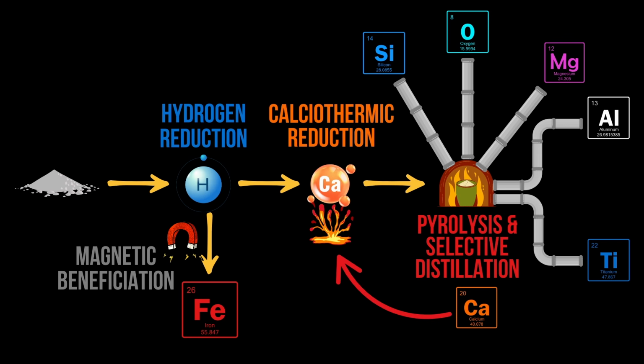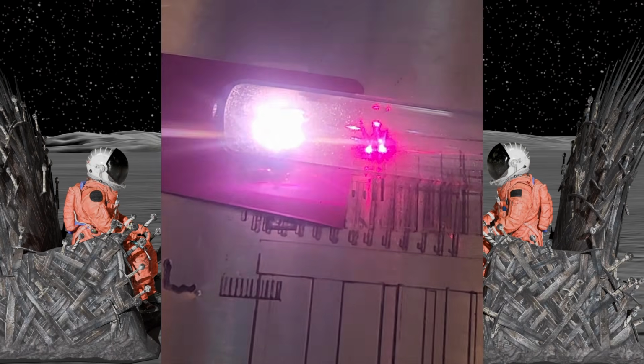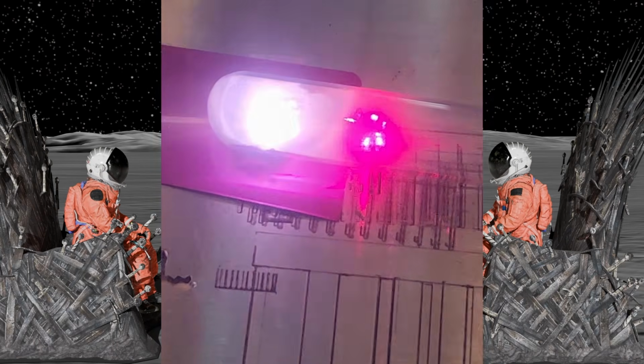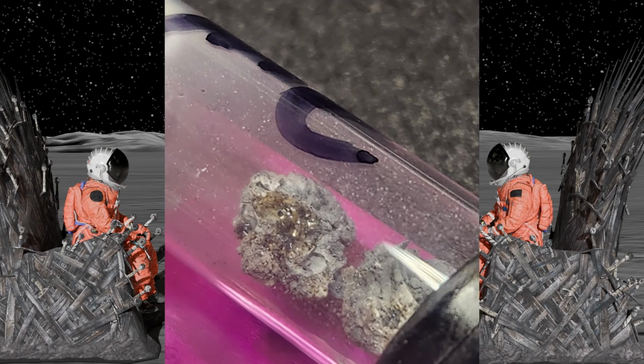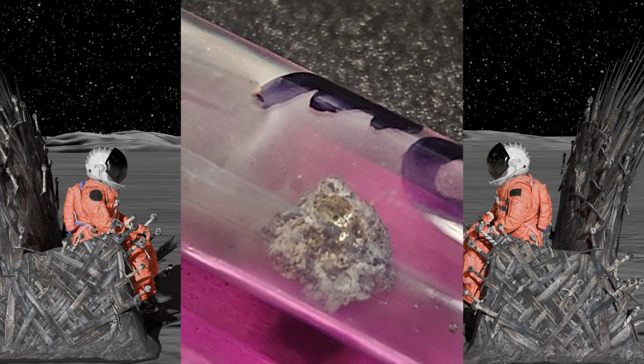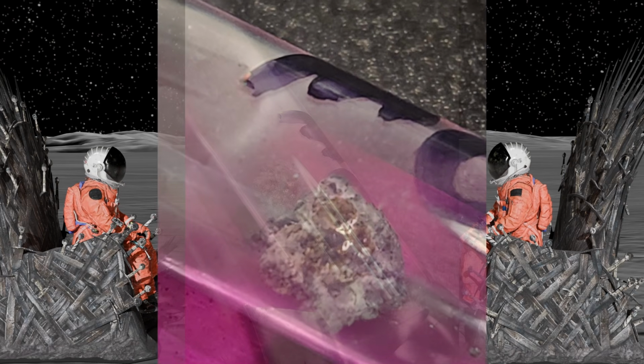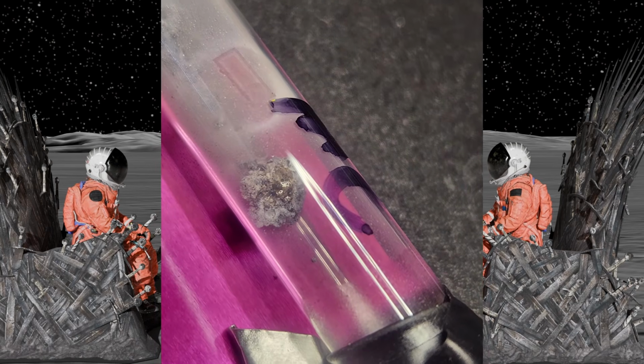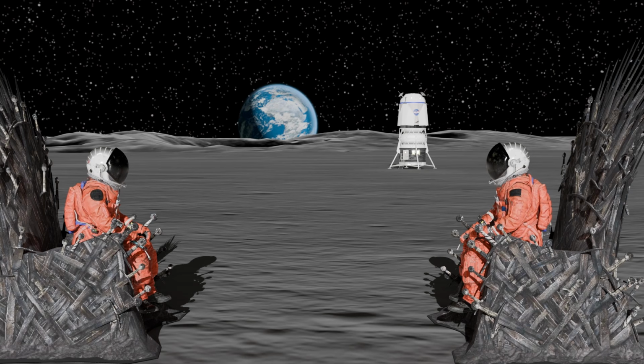You were able to use the laser on the slag, or on the alloy cake that we got when we did the calciothermic reduction, and you were able to return golden pure calcium for a second before it reoxidized with the oxygen in the tube. But it showed that pyrolysis should also work on this calcium oxide so we can get our closed feedback loop. Yeah, so in the initial phase, you're going to need a lot of calcium. So you're going to start with electrolysis probably.